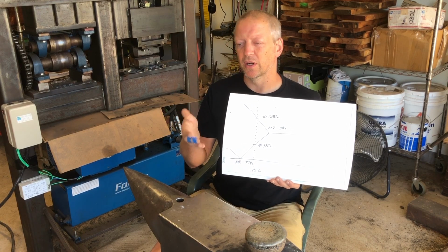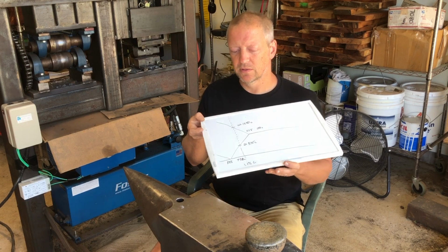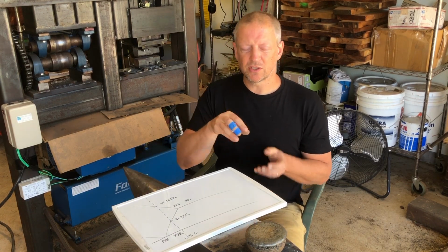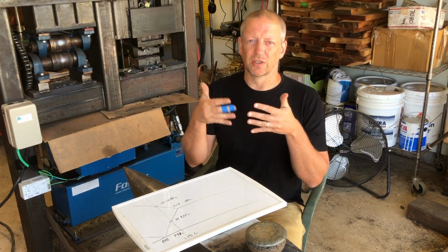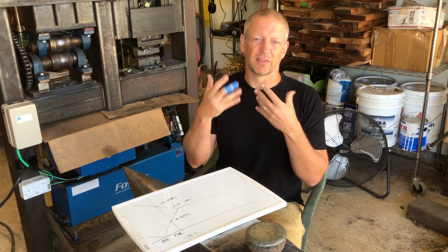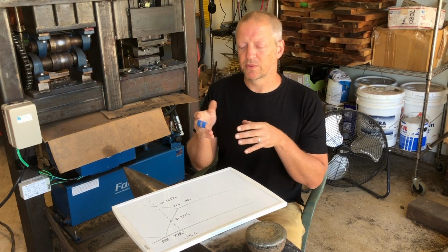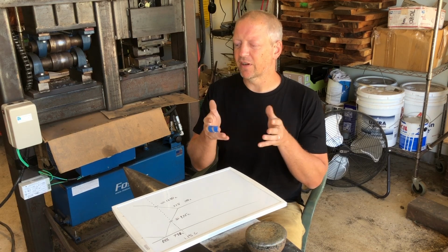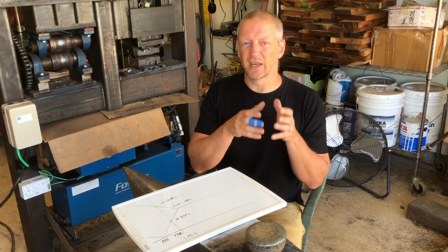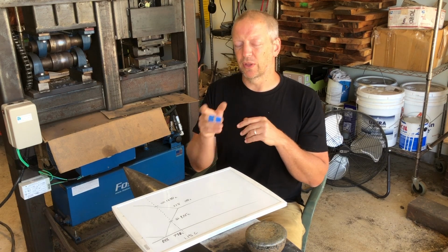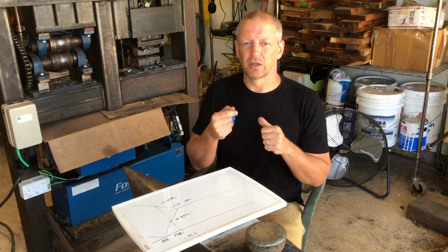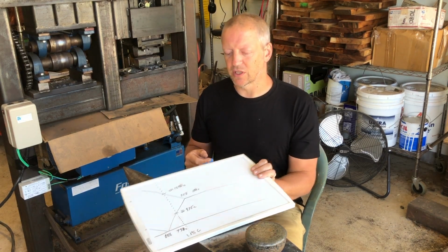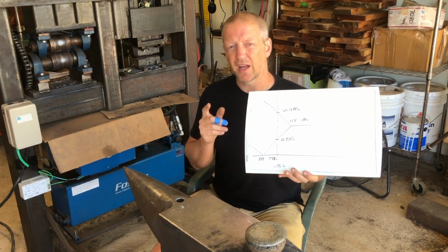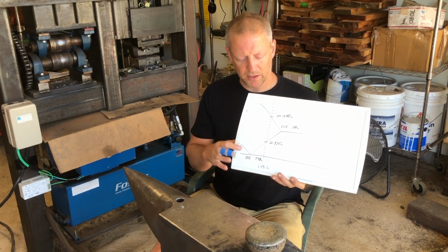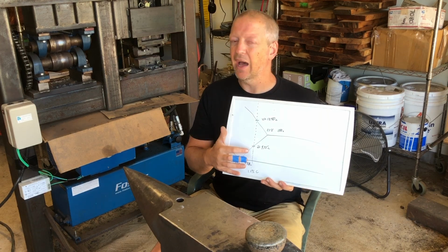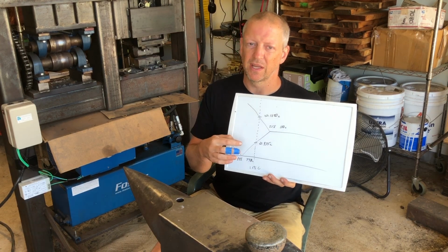Because like I was saying before, when you start out, the grain structure and the dendritic structure are pretty closely aligned, and that's a very brittle setup. So at the very least, you want to change that initial grain structure so that it's no longer aligned as closely with the dendrites. Now, a couple follow-up points. One, I do suggest not soaking just below A cm.